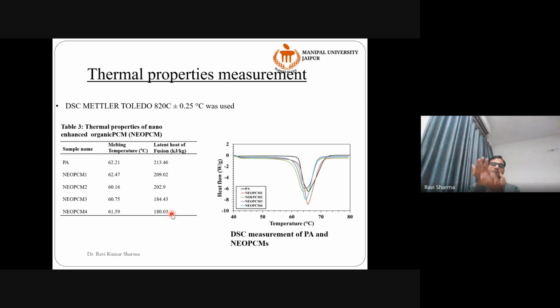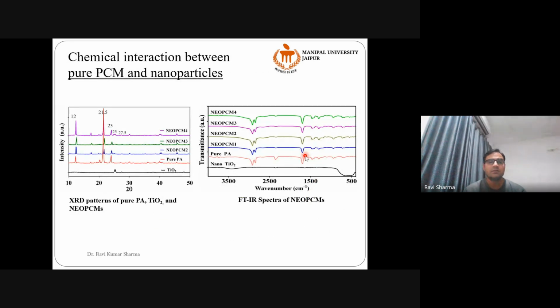These nanoparticles will bring down the specific heat of the PCM, meaning the latent heat of the effective composite will be lesser compared to the pure PCM. As we keep increasing the amount of nanoparticle, the latent heat will keep decreasing. These values were obtained from the differential scanning calorimeter thermogram. Now let's look at what happens to the chemical stability.